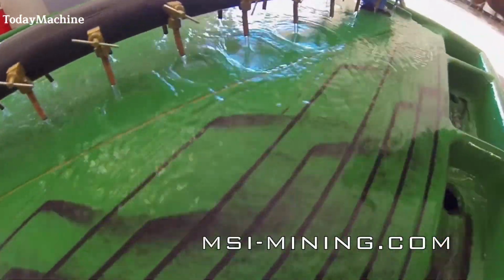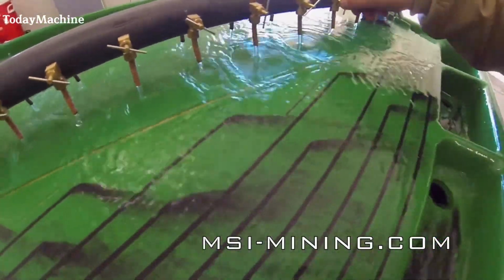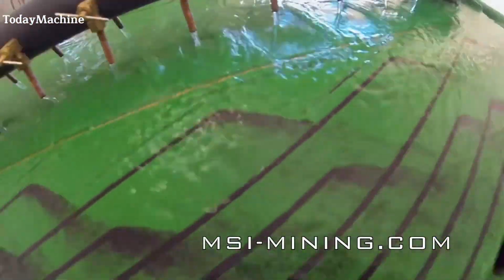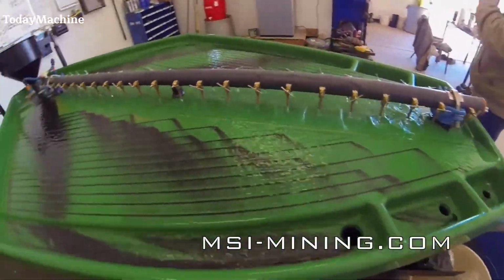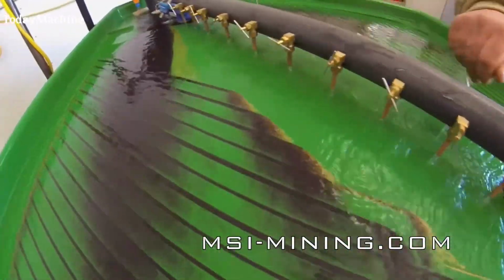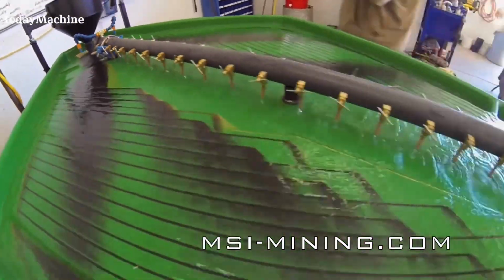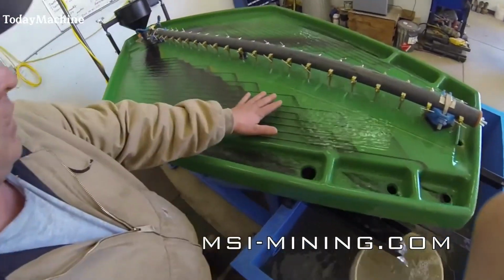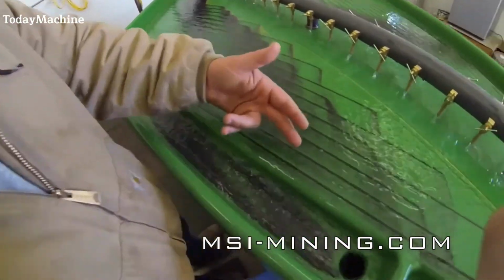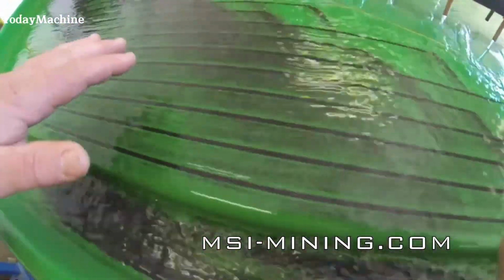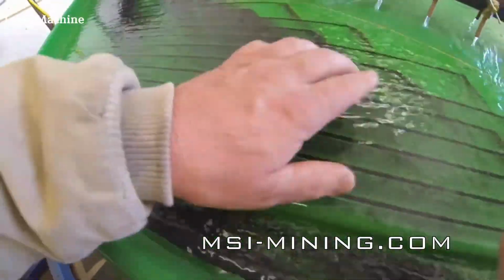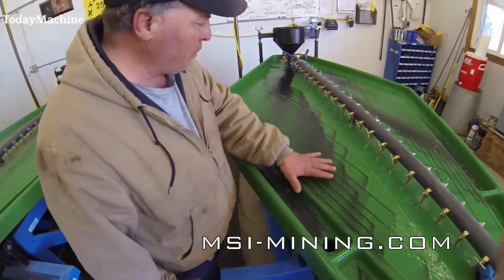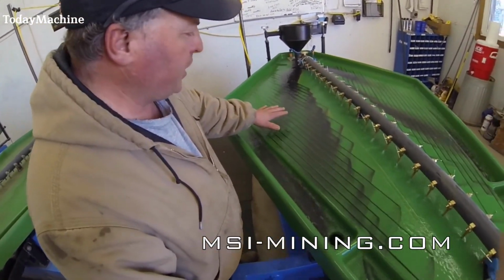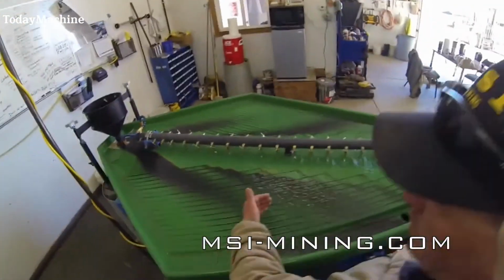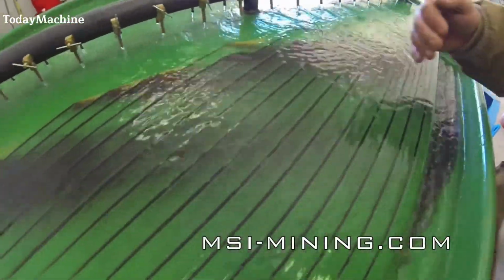Check the distribution of materials. The table should show a clear gradient, with light sands separated from heavier black sands and gold. Ensure that the green surface of the table remains visible through the black sands to prevent material buildup and losses. After processing, collect the gold concentrate from the cut lines. If any gold particles are mixed with black sands, they can be captured in subsequent cut lines for reprocessing.